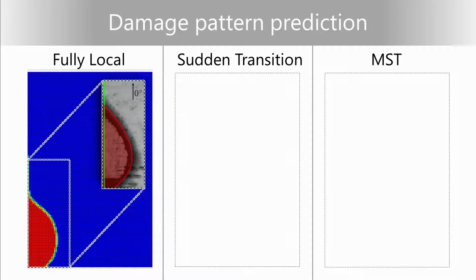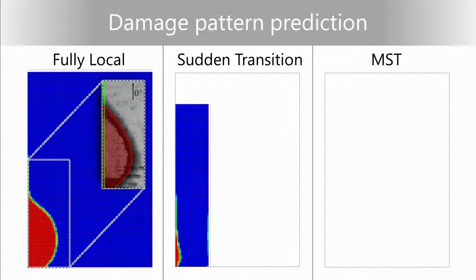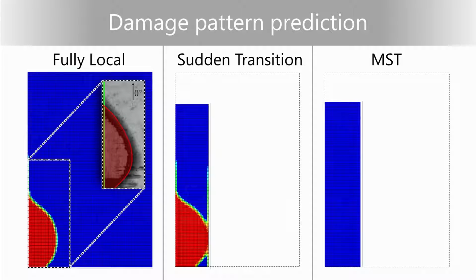If I show you now just the 3-dimensional part, so the local part of the model with a sudden transition, you can see that as the delamination grows, you get some damage at the intersection between the refined model and the shell model. And this is to be expected because you have some stress concentrations there. Now, if I show you the same thing for the mesh superposition technique model, now you have exactly the same size of the local mesh, so absolutely no difference, but you obtain the same result as in the fully local model.